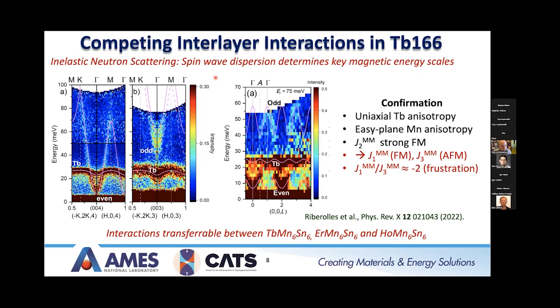So, competing interactions in terbium 166. These are some of our inelastic neutron scattering data that we took on ARCS using the sweep mode. And you can see we get these very nice pictures of the even manganese modes coming down here. We're showing across the minus K, 2K4. So you see this manganese mode come down. You get the gap right at 004. And then we have the odd mode here, looking around 003, you can see the minimum in the odd mode.